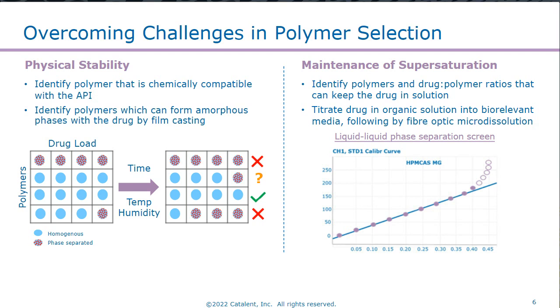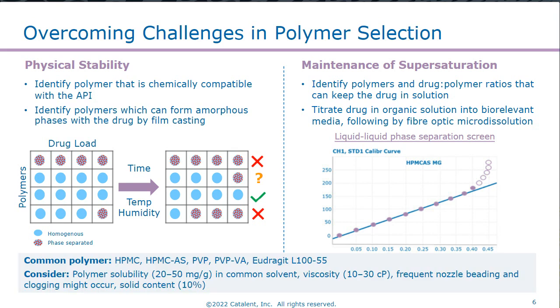And by identifying where that separation occurs, we can determine how much polymer is required to maintain the drug in solution. So from a combination of those two experiments, we can determine which polymers at which drug loads are going to be physically stable, and we can determine which polymers at which drug loads are going to maintain the supersaturation. And so we can identify which of the polymers are worth spray drying.